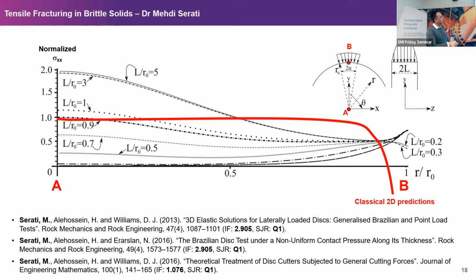What happens if the distribution of the load along the thickness of the sample is not uniform? What would happen if there is a violation of that? For instance, during the coring process, or there is a grain that has a different stiffness. What happens if you cannot safely assume that it's uniformly distributed along the thickness?